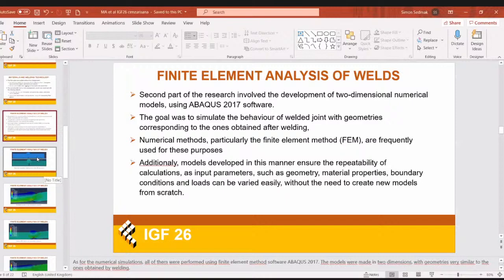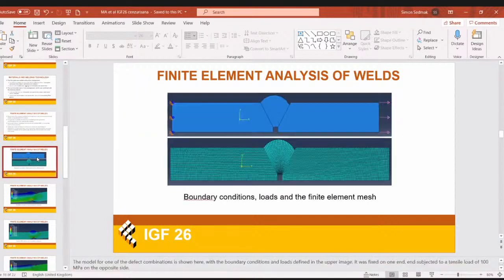And the first stage was to make the models based on the real geometries in Abaqus. And here you can see an example of one of these models with the excess weld metal, the undercut, and the incomplete root penetration. With its boundary condition, it was fixed on one end and subjected to tensile loads on the other. And here you can also see the mesh.